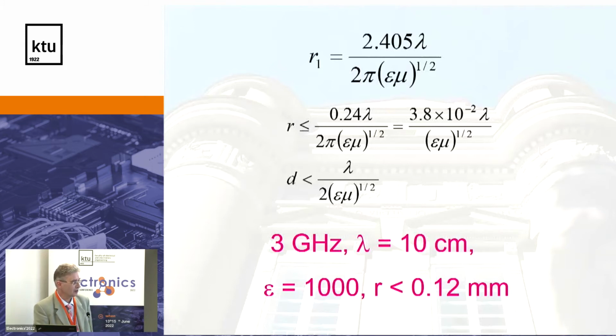And we learned that, let's say we have 3 gigahertz frequency, then the electromagnetic wavelength is 10 centimeters. And if we have barium titanate, which has more than 1000, let's assume we have an electric permittivity of 1000 only, the radius of a sample should be less than 0.12 millimeter. If the sample is wider or bigger, you will have a non-homogeneous distribution of the electric field, and the simple capacitance formula will not work. So the results that you get will be fake, like fake news, which is now popular.